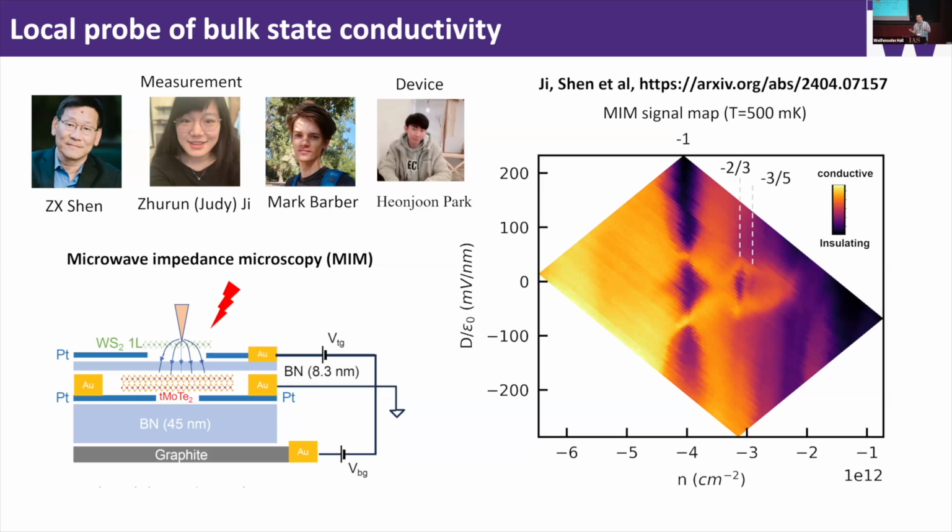What's magic here is that these photocarriers are mobile enough to make the monolayer WS2 a good gate, but at the same time not mobile enough to screen out the tip. So from this light-coupled monolayer WS2 lying on top of the sample, we can measure the local conductivity inside the sample.